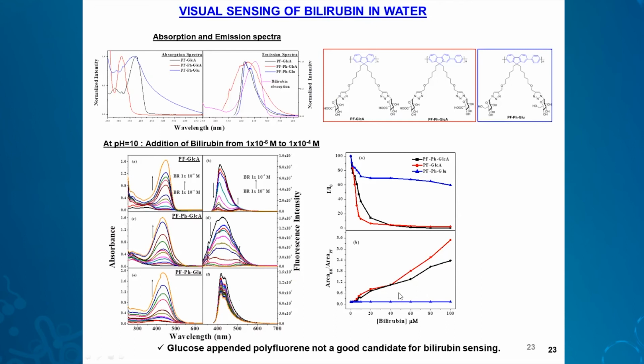So here is shown the plot in different ways. That is the area of the quenching of this versus the increase of the bilirubin fluorescence, or the quenching of this intensity. You can see that the blue one, that is the glucose, is not a good polymer. This was the reason, because the glucose appendage did not make the polymer very much water soluble. It was water soluble, but not to the extent of the other two polymers. So these two were taken forward for the study in blood serum.